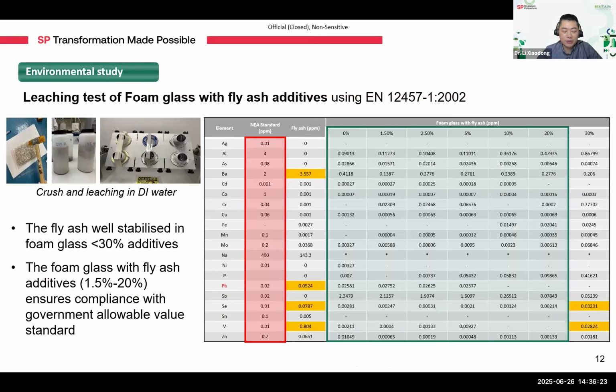While developing these materials, we are also mindful of environmental safety, especially under conditions like rain or moisture exposure. We wanted to ensure the heavy metals in the fly ash won't leach into the environment. So we conducted a standardized leaching test following the guidelines from Singapore's National Environmental Agency. Here, what we did, we crushed the foam glass samples, immersed them in deionized water, and then rotated the mixture for 24 hours before analyzing it using ICP-OES.